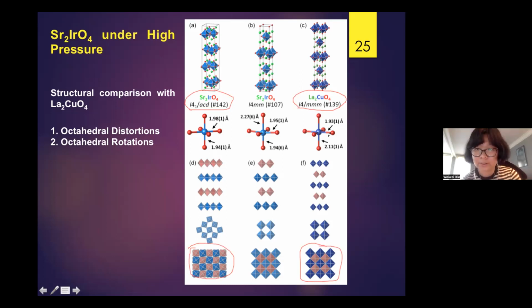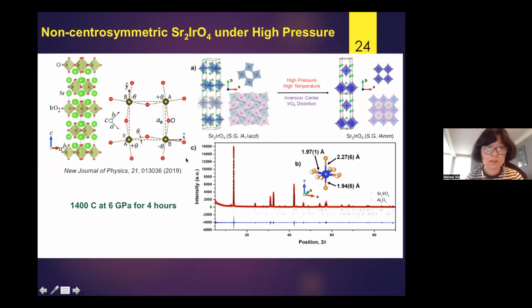Also, we see the distance for the octahedra. That makes us think: can we pressurize strontium-2 iridium-O4, with high pressure and high temperature, and see what we can find out? That's where the idea comes from. What we found is a completely new strontium-2 iridium-O4 phase, which is non-centrosymmetric. We made it under high pressure, 1,400 degrees Celsius and 6 GPa. We just heated it for 4 hours, and this is the new phase we got.